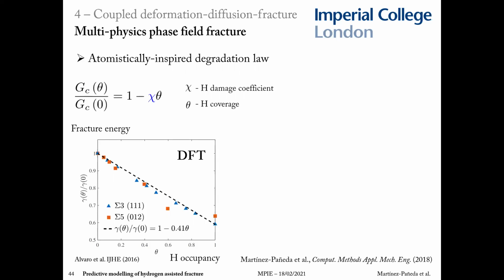In our case, we want to follow the rationale that I outlined before. So we establish a direct quantitative connection with the atomistic calculations that I discussed before, which tells us how the surface or the fracture energy is reduced with hydrogen coverage. So we can run atomistic calculations offline and use them to define a degradation law that has no fitting parameters. For example, in nickel, based on these DFT calculations, you can define a linear degradation law where this variable chi is the hydrogen damage coefficient, which equals 0.41. So there's nothing really to fit there.